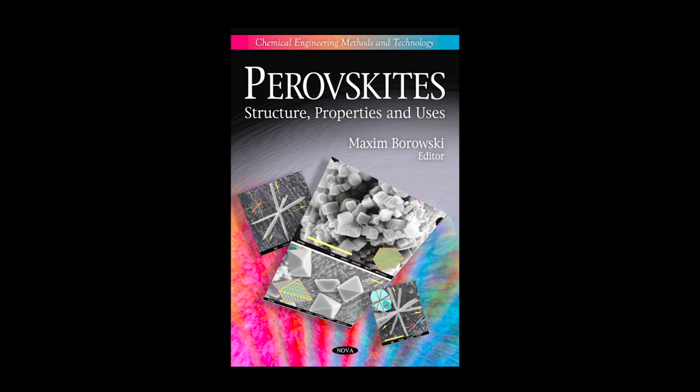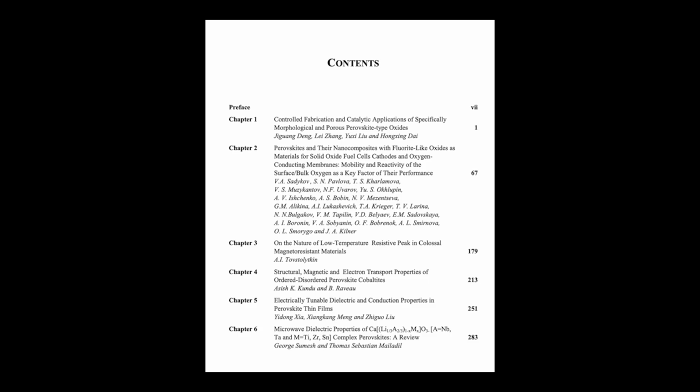These defects create localized electronic energy states deep within the material's band gap. When the material is excited, say by UV light, electrons and holes get trapped at these defect states. The light emission we then see results from electronic transitions between these localized defect energy states and the conduction or valence band edges, or even between different defect states. For example, those lead titanate, PbTiO3, nanowires we mentioned earlier show a distinct blue light emission band centered around 471 nanometers.